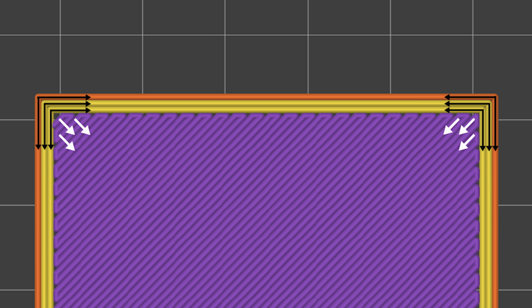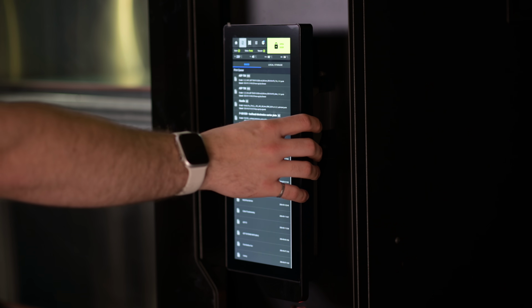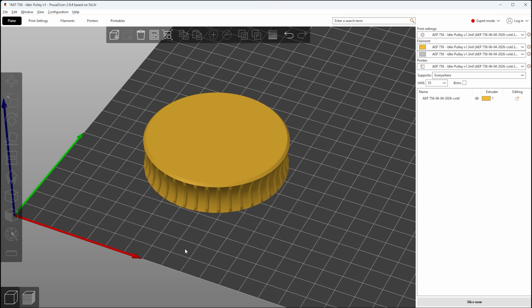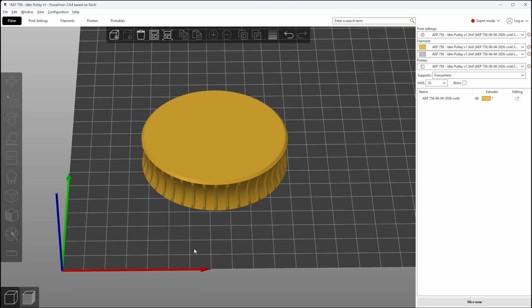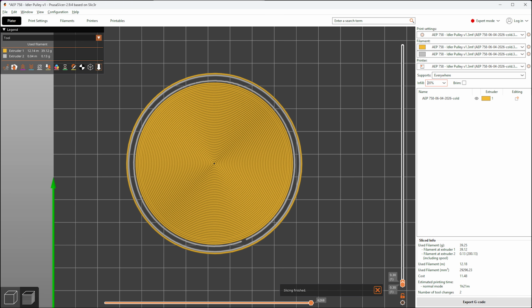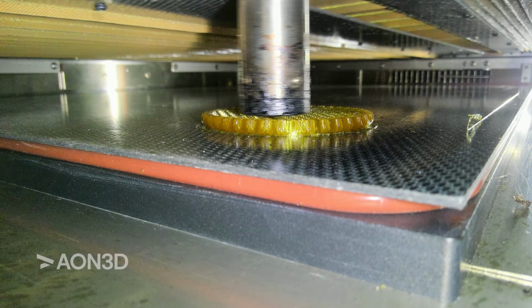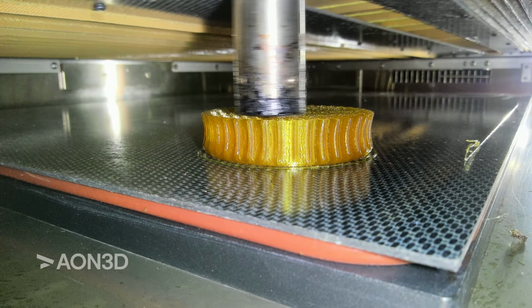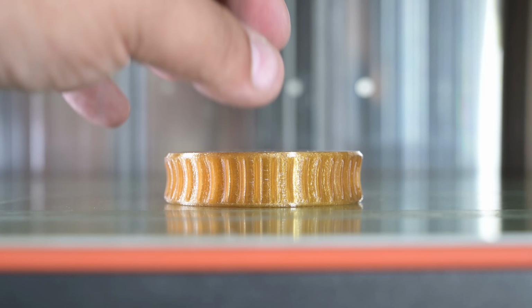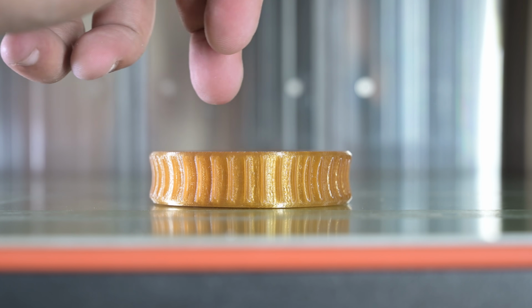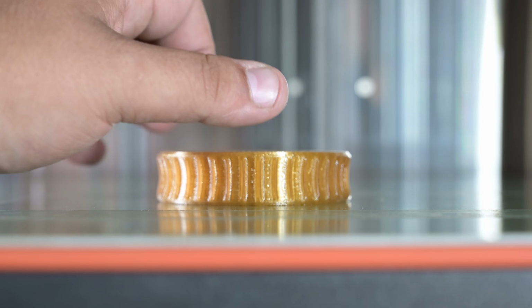Even then, it wasn't as simple as pressing print. After countless attempts, we still had to modify the geometry. We switched to a concentric base infill, applied an adhesion aid, and reduced the infill to a bare minimum before we could produce a successful part. And even then, the part contained dimensional accuracy issues due to premature cooling.